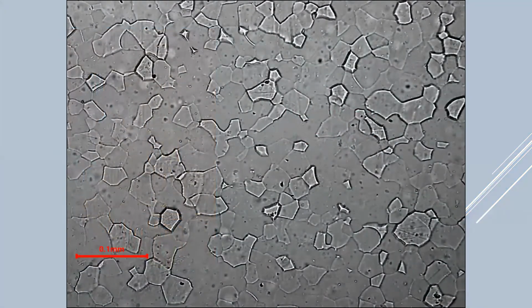So rim steels have that really thick layer of almost pure ferrite on the surface. And when it gets rolled into a plate, all that happens is that thick layer gets squished down. It's all in proportion. So in a plate, you'll have a layer of almost pure ferrite on the surface, and that'll still persist even on the plate. And that's what we've got here. So I took an in situ replica of this pressure vessel. That's what we see here. That whole surface, all we're seeing here is grains of ferrite, nothing else.